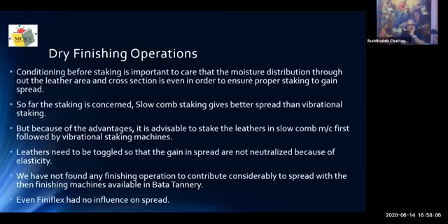Conditioning before staking is important. The moisture should be distributed not only throughout the area of the leather, but also throughout the cross section. And you must give proper time for this to even out the moisture content. As far as staking is concerned, slow comb staking gives a better spread than vibrational staking. But because of the advantage, it is advisable to stake the leather in a slow comb machine first, followed by a vibrational staking machine. Leather needs to be toggled so that the gain in spread during staking is not neutralized because of the elasticity of leather.